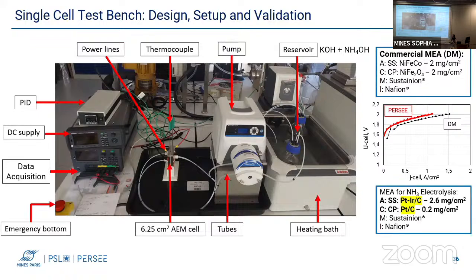In order to recover hydrogen from ammonia using this test bench, it is necessary to adapt the material of the electrodes, specifically replacing the nickel-based catalysts with platinum-based ones. Due to time limitations, we will use commercially available cathodes, and the work will focus on the preparation of the anodes.